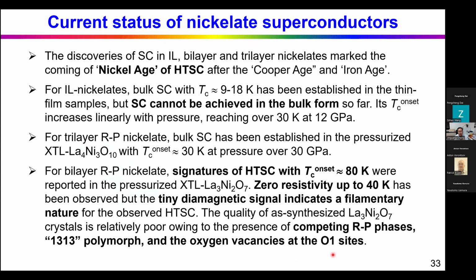So let me summarize the current status of the nickelate superconductors. The discovery of superconductivity in the infinite layer, bilayer, and trilayer nickelates marked the coming of the nickel age of high TC superconductivity, after the copper age and iron age. For the infinite layer nickelate, bulk superconductivity with TC around 9 to 18 Kelvin has been established in thin film samples, but superconductivity cannot be achieved in the bulk form so far.